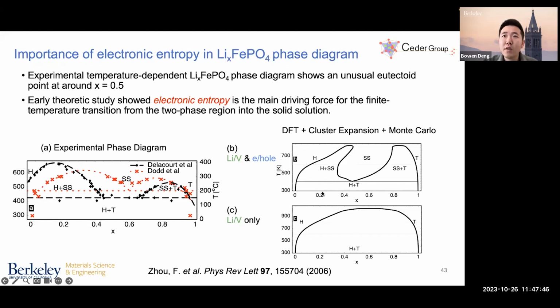And figure B and C are both simulations from DFT with cluster expansion methods, which allow Monte Carlo sampling. With the difference that figure B considers both ionic and electronic entropy from lithium vacancy and electron hole, while figure C only considers the distribution of lithium vacancy. And the correct physics involved in this eutectoid transition is only captured in a model where both ionic and electronic degrees of freedom are considered, where figure C shows only a simple miscibility gap that does not match the experimental phase diagram.